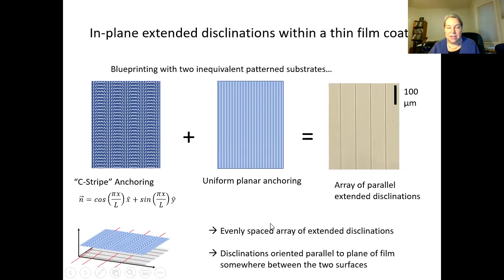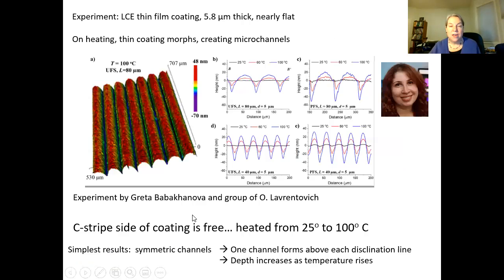They are fascinating things. Here is a little mock-up picture. On one surface, you have this patterned thing. On the other side, you have this uniform thing. And in between magically forms this parallel array of defect lines. If you build that, then take one surface, take the glass off, and heat it up, it forms little microchannels. So this is an actuatable coating, a programmable actuatable coating.